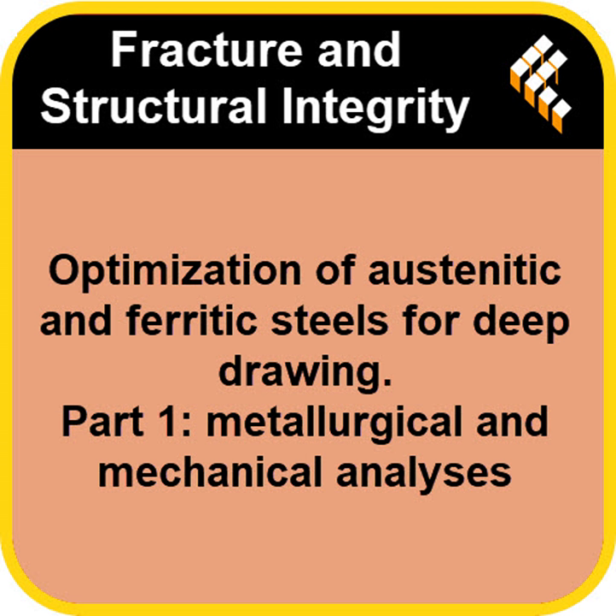Wow. Why would grease do nothing? It comes down to pressure. Deep drawing uses really high blank holder pressures to control the metal flow. Right, clamping it down. Exactly. And that high pressure just tends to squeeze out viscous, liquidy lubricants like petroleum jelly. It physically pushes the lubricant away from the contact zone. Like stepping on a tube of toothpaste, it just squirts out the sides. That's a great analogy. So you'd end up with metal-on-metal contact, dry sliding, right where you need the lubrication most. The solid PVC film doesn't get squeezed out. It stays put.